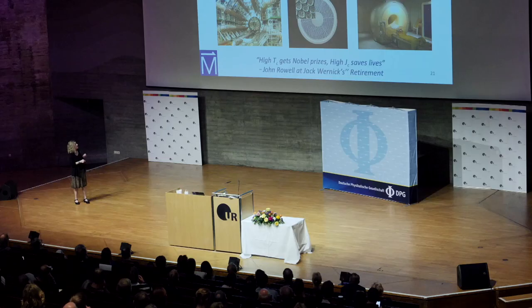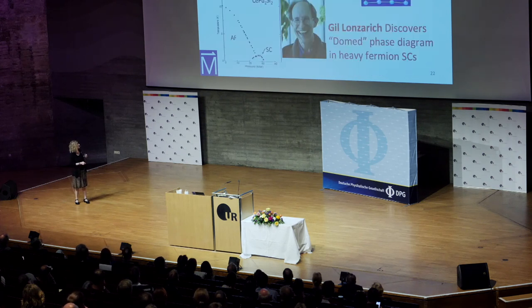It's very brittle. So what he then used, at Rutherford Appleton Labs, was a random alloy of niobium titanium that was discovered. Where the crystal structure was so important, and if you mess up the crystal structure you destroy the superconductivity, this random alloy has a lower TC, a lower HC2, but it's the workhorse of the industry. That's what's used in the colliders and in MRIs. So unless you have to go to higher TC and HC2, this is the workhorse of the field. But I will say that CERN is looking into using the A15s now, and there are other steps forward.